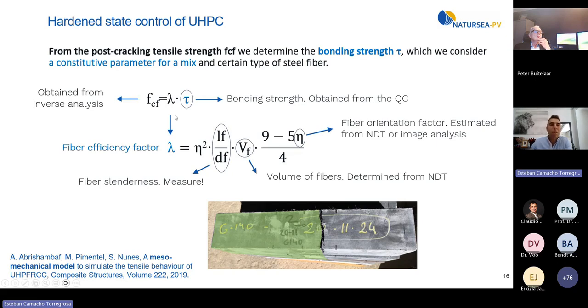This procedure shows that the post-cracking tensile strength is the fiber efficiency factor lambda multiplied by the bonding strength. Here we have the post-cracking tensile strength because we obtain it from the quality control. We don't know the bonding strength, but we can obtain the fiber efficiency factor. Fiber efficiency factor means how much amount of fiber I have, or how much performance of fiber I have.